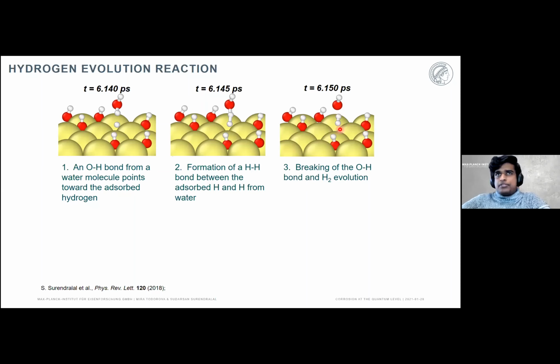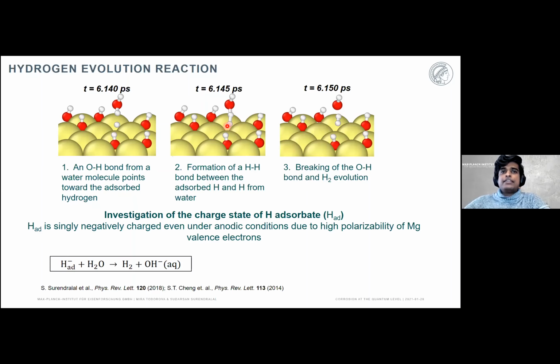And this is the mechanism of the hydrogen evolution. However, something that was very puzzling is this certain configuration. Because you expect the hydrogen that is attached to a water molecule to have a slightly positive charge, which means the only way that such a bond can be established electrostatically is if this hydrogen that is adsorbed on the surface is negatively charged. And this is exactly what we find from a charge density analysis scheme.